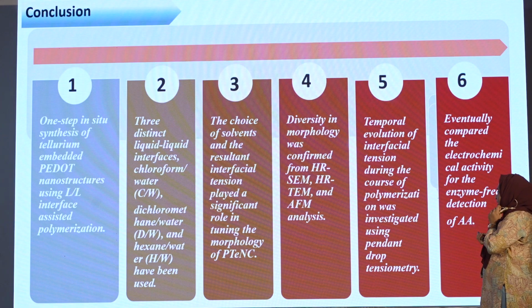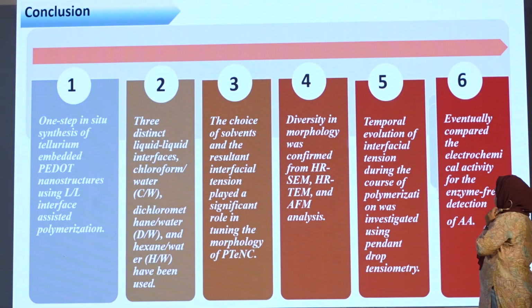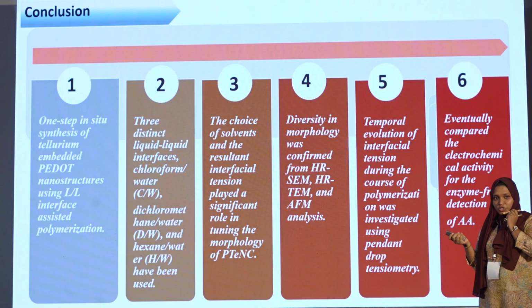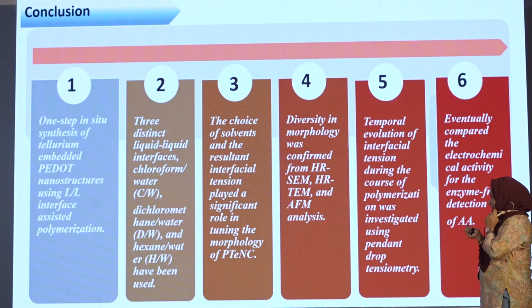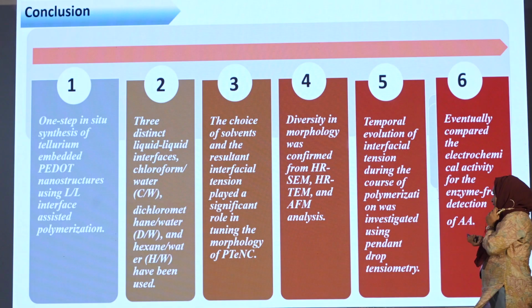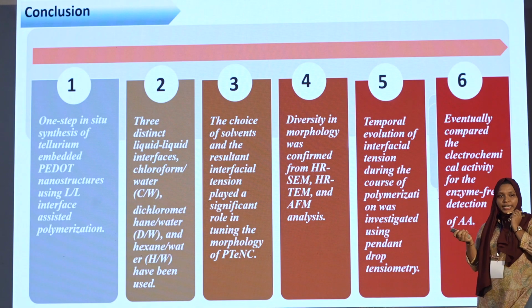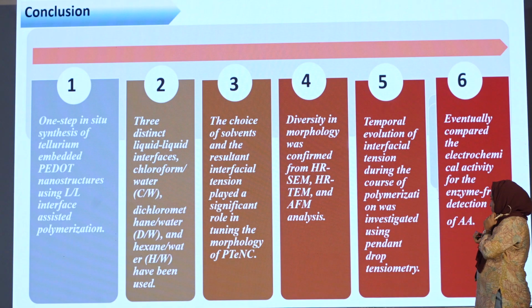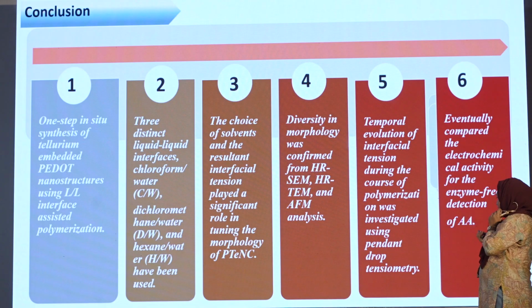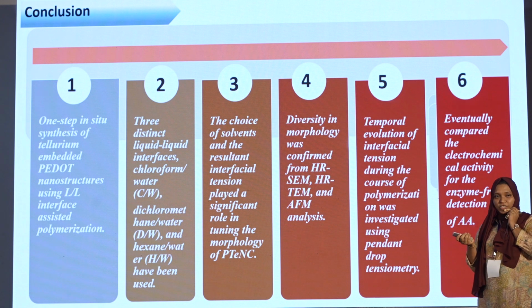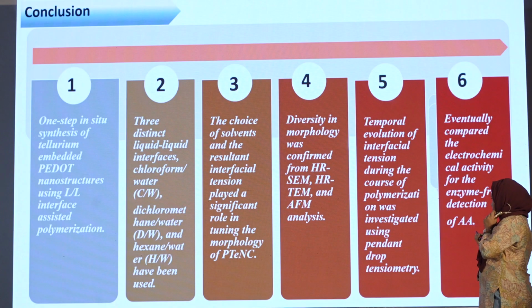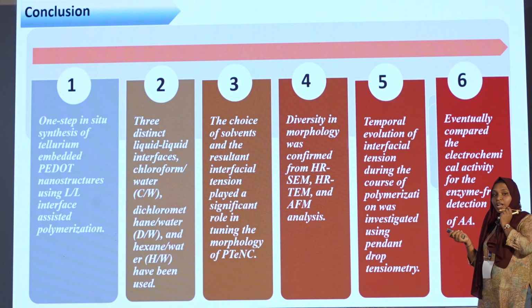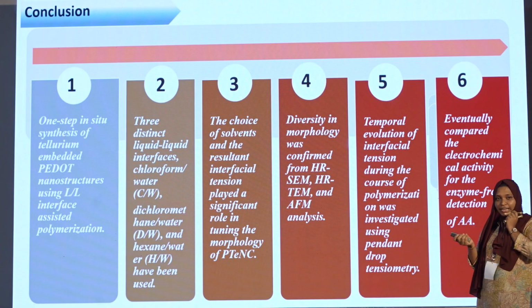So in conclusion, one-step in situ synthesis of tellurium-embedded PEDOT nanostructures using liquid-liquid interface-assisted polymerization has been done. Three distinct liquid-liquid interfaces of chloroform-water, dichloromethane-water, and hexane-water have been used. The choice of solvents and the interfacial tension played an integral role in determining the morphology of the structures. Diversity in the structures was confirmed from HRSEM, HRTEM and AFM analysis.